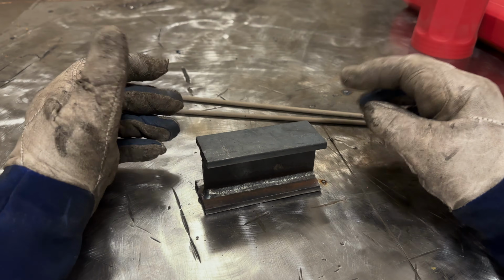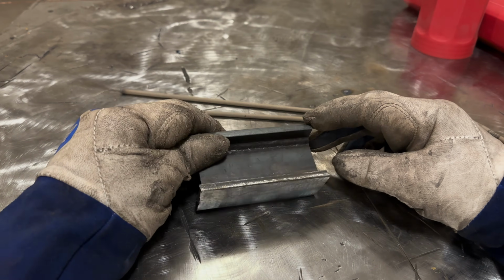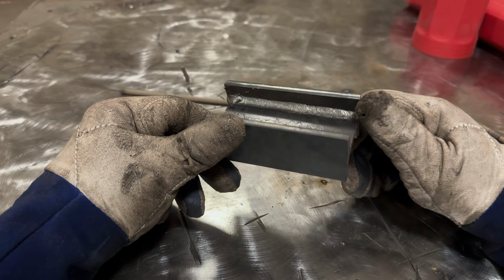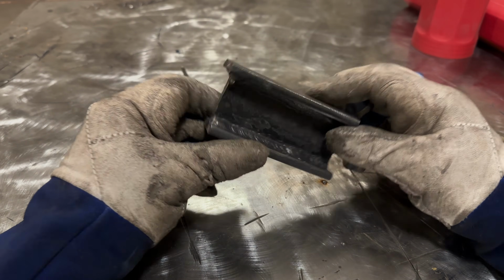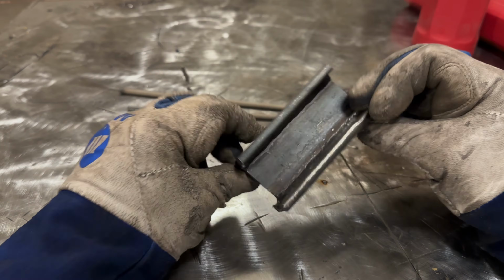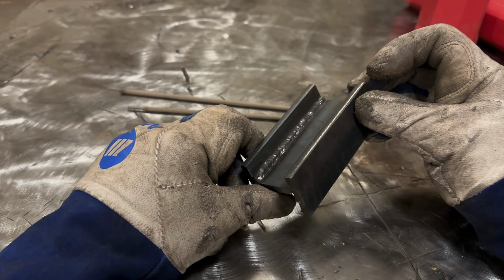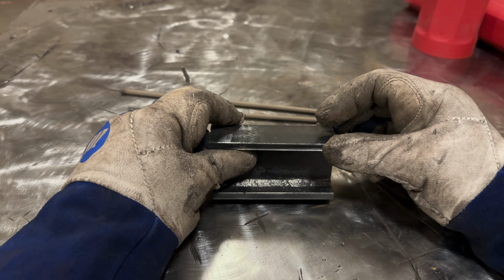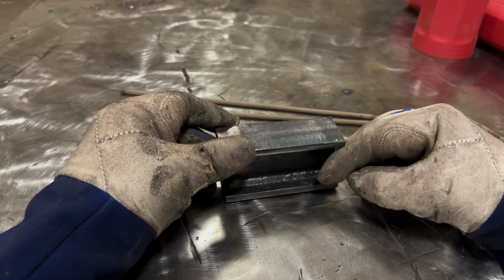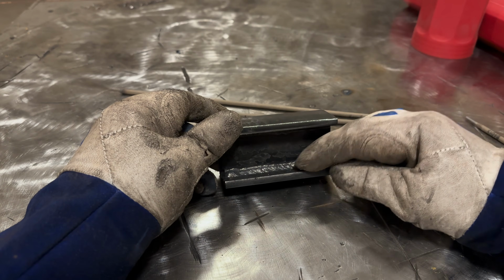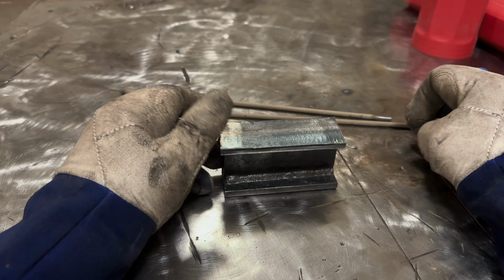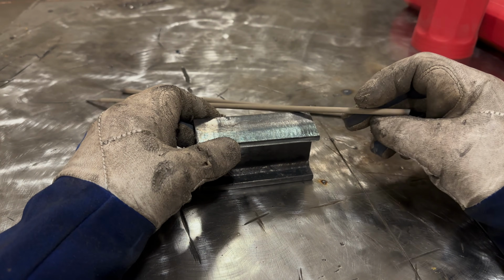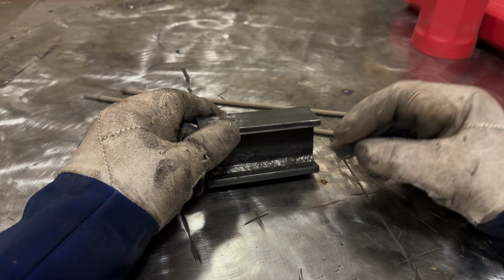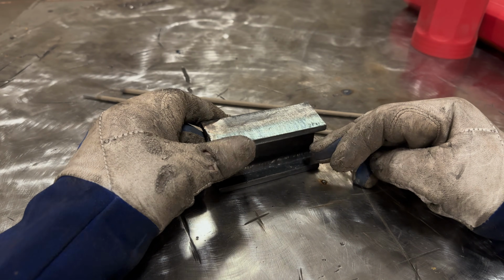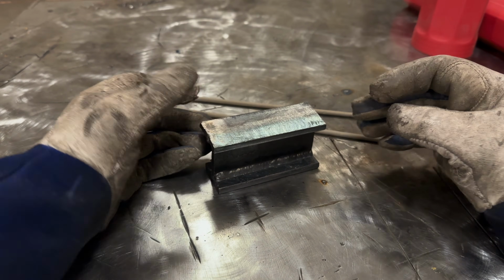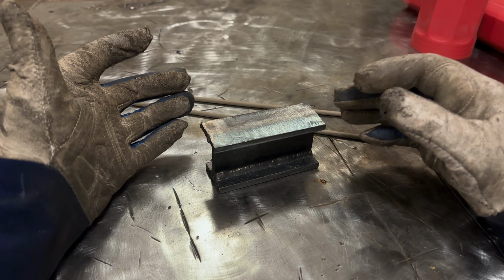Now, another thing that can cause arc wandering is if you don't prep your material well. Look at this, I did this for a previous test, but I didn't do a lot of prep work on this top plate. Now this side I did. What can happen is as you're welding, if you hit a bunch of mill scale or oil, it can cause a gas buildup inside of the weld, and then it can just spit it out, which could break the flux off the end or melt it off in an unusual pattern, and then next thing you know, you get arc wandering.